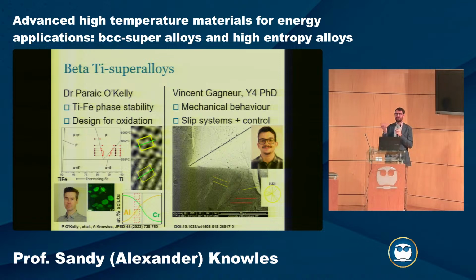I mean, you might think titanium and iron are quite industrially used very widely, both titanium alloys and steel metallurgy. You might think that the understanding of how titanium and iron are mixed together is very well understood, but we found that actually there's quite a lot of people haven't looked into these spaces between the two elements in great detail. So we looked at both the phase equilibria, so we can do things like SEM EDX, scanning electron microscopy, where we can identify the precipitates and measure their composition.